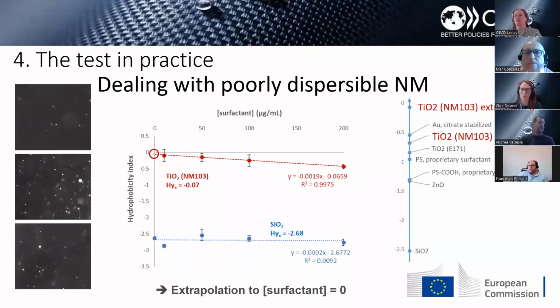This is really important because without this extrapolation method, you cannot have a hydrophobicity index for hydrophobic materials that are not dispersible in aqueous medium. On the right, you can also see a scale of the different values of the hydrophobicity index for different tested materials.